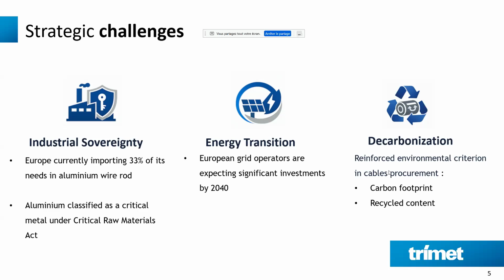But we don't want to stop from this, and that's where we were very interested in looking at the possibility to increase recycling content in aluminum rod, which has never been done in the past because of the different things that Stefan explained about conductivity and so on, and also the difficulty to capture this kind of scrap, which we can use in aluminum production for wire rod.